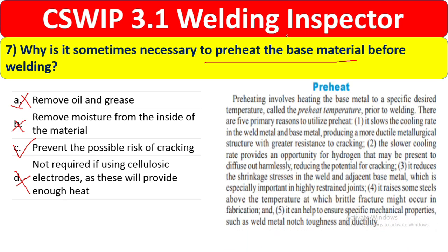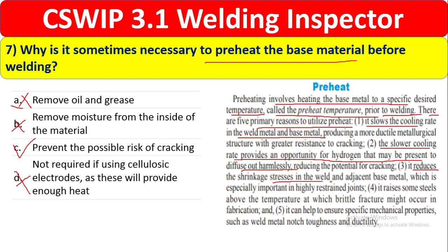You see here, the preheat details are mentioned. Preheat involves heating the base metal to a specific desired temperature, called the preheat temperature, prior to welding. There are 5 primary reasons for utilizing preheat. First, it slows the cooling rate in the weld metal and base metal. Second, the slower cooling rate provides an opportunity for any hydrogen present to diffuse out harmlessly. Third, it reduces shrinkage stress in the weld and the adjacent base metal. Fourth, it raises steel above the temperature at which brittle fracture might occur in fabrication. And fifth, it can help to ensure specific mechanical properties.